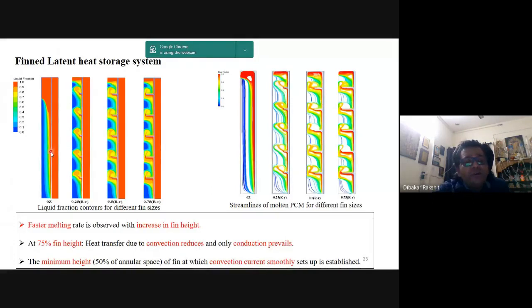Of course, we started with no fin, where we only have the mannitol, and then we introduced the fins. Eventually, we increased the height of the fins. As I told, up to a certain point there is meaning in increasing the height of the fins, beyond which it has no impact. So we wanted to find out the optimum fin height where the convective currents don't get interfered with by the conduction happening through the fin. Through the CFD analysis, we found that at 3/4 of the fin height, the heat transfer due to convection reduces and only conduction prevails. So the minimum height we should keep should be around 50% of the annulus.